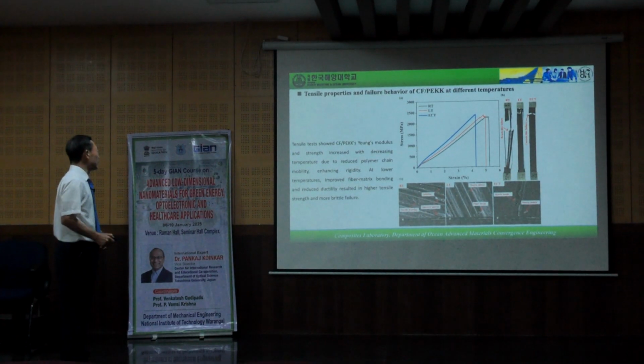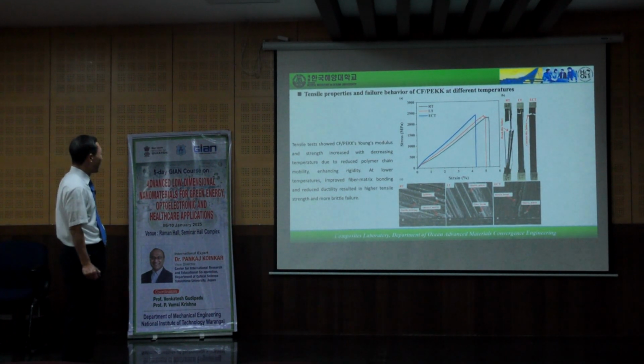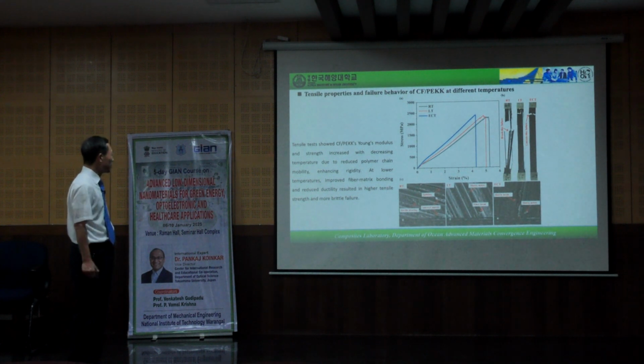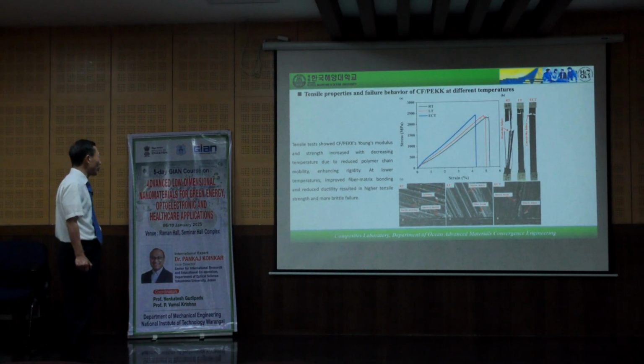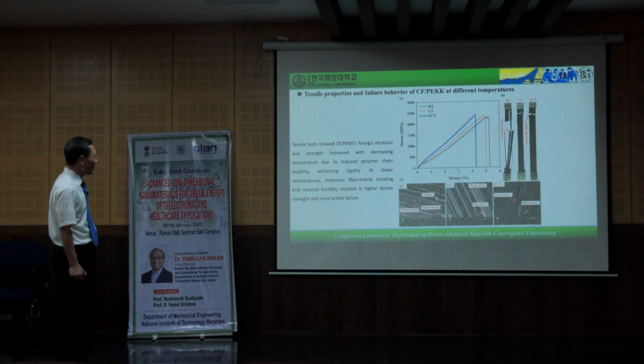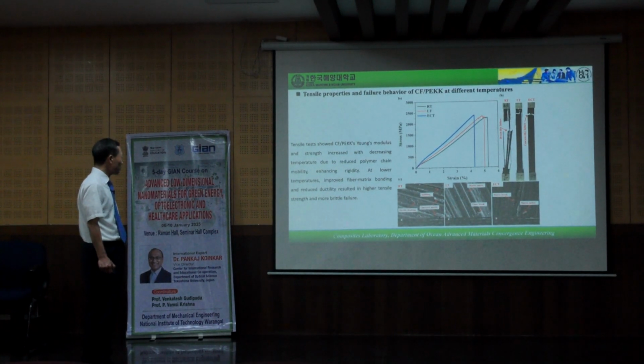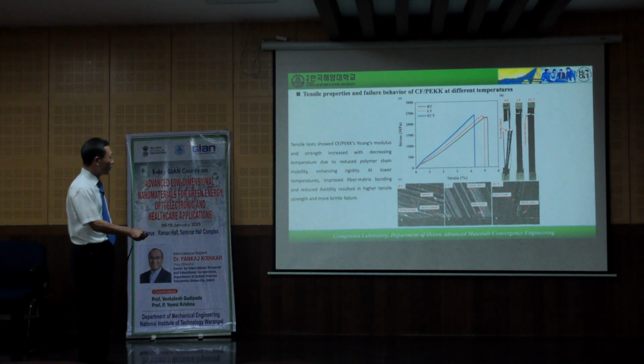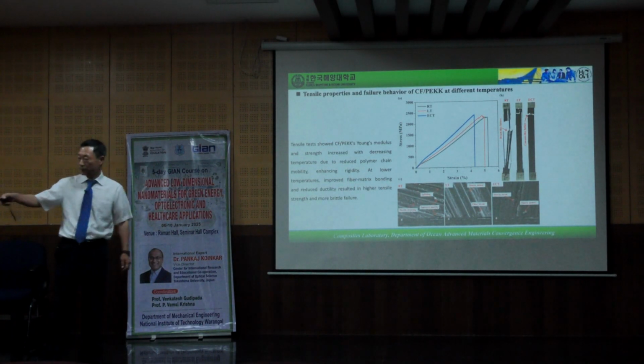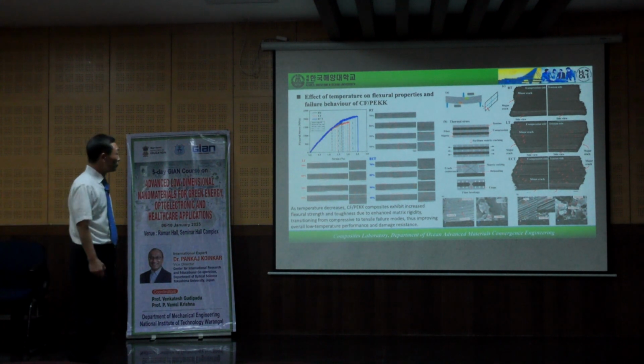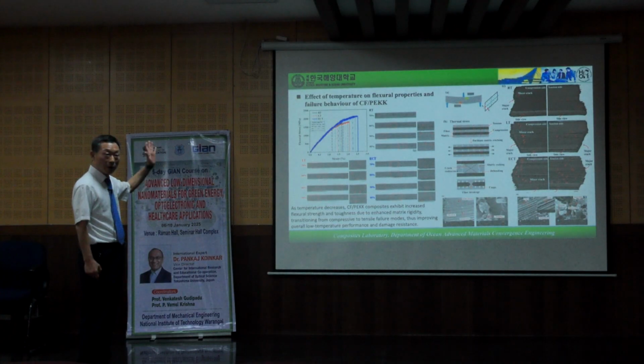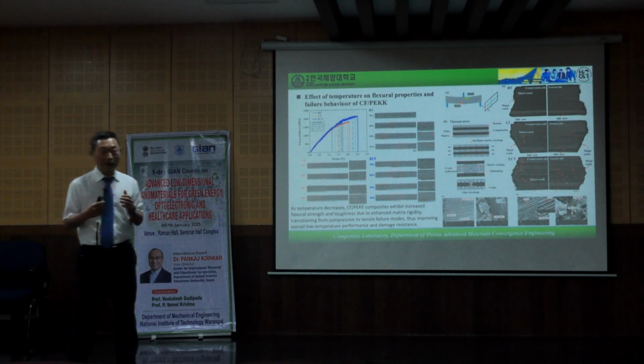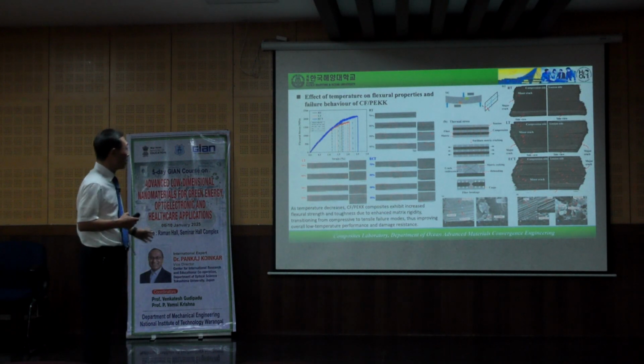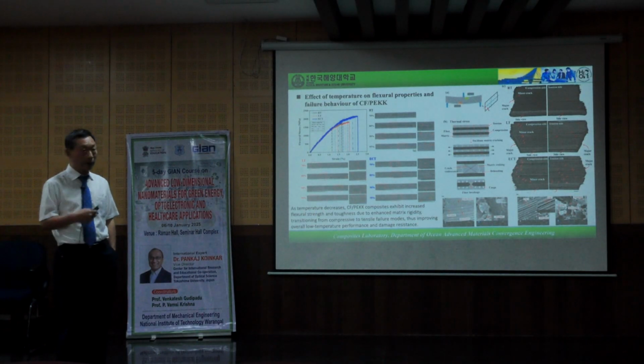So this slide means tensile tests show the CF/PEKK Young's modulus and the strength increased with decreasing temperature due to reduced polymer chain mobility, enhancing rigidity. At the lower temperatures, improved fiber matrix bonding and reduced ductility resulted in higher tensile strength and more brittle fracture. This kind of result was published in Composites Part A. The impact factor is more than 7. A very good journal.